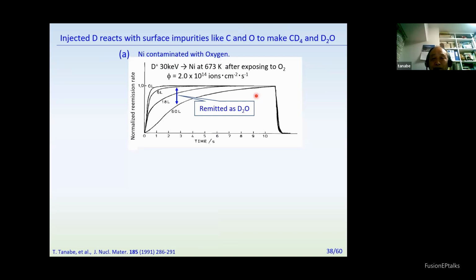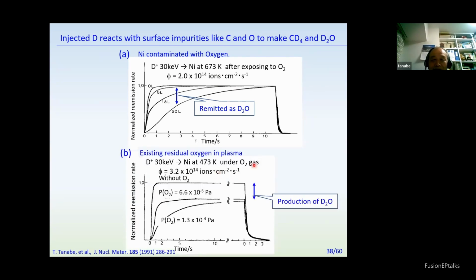Also, hydrogen reacts with oxygen and carbon—this chemical element carbon leads to the formation of methane. If there is oxygen on the surface, deuterium implanted in nickel can remove this oxygen, forming D2O, or react with oxygen existing in the surrounding atmosphere to produce D2O. So the chemistry is very active.